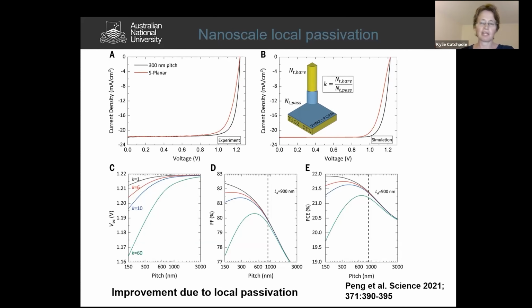And we also varied the ratio of the recombination at the bare and the passivated layers. And you can see that what we found is that we've got a very good fit to the results when that bare area in the yellow had about 10 times the recombination of the passivated layer. And in that case, that provided a very good explanation of why we had particularly good results for the 300 nanometer pitch. And you can see that we have good agreement there between the experiment and the simulation.